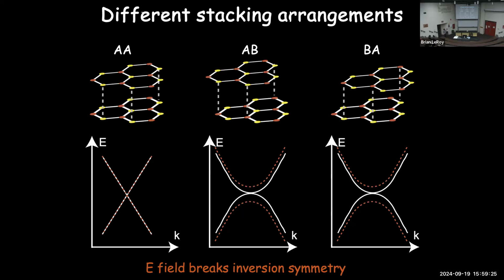If you stack the graphene in this AB or Bernal stacked configuration, you have basically the yellow atom here directly above a red atom here. In that case, the dispersion relation becomes quadratic. Energy versus momentum relation becomes quadratic here. If you stack it in the opposite configuration, the BA, so red over yellow instead of yellow over red, that's going to be exactly equivalent. It's just flipped over. It's like looking at it from the other direction. So you should have the exact same energy versus momentum relation.